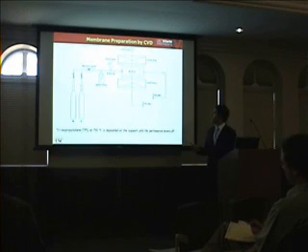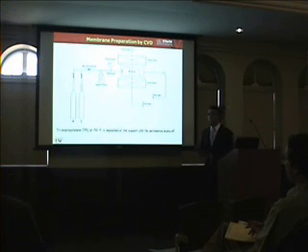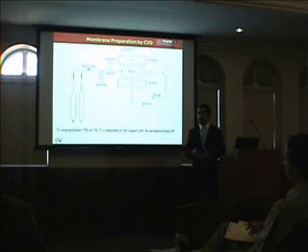So this is the reactor in which we make this membrane. Basically this is our CVD reactor. We put one of those supports here, and our source for silicon carbide is a polymeric precursor called triisopropylsilane. It's injected through the syringe pump. It's preheated first to evaporate, and then it's carried by argon into the reactor. We operate our experiment at between 700 to 800 degrees C.